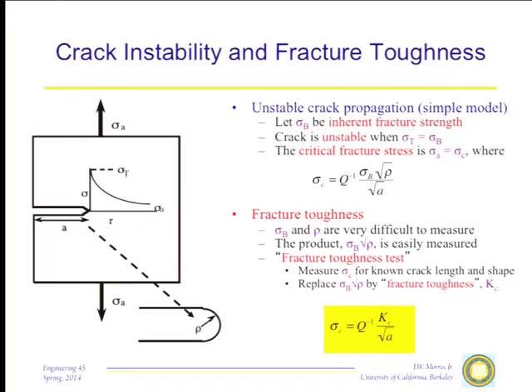Then let me just do a test. I put a crack in of known length and known geometry. I load it as sharp as I can make it, load the sample up until it becomes unstable. So I've measured sigma c, I've measured Q, and I know A. So I can therefore measure the fracture toughness Kc. Now that's the product of a couple of things I'd have trouble measuring individually, but I don't really care because what I want to know is this. I'm going to be able to predict the breaking stress. So this is what's called the fracture toughness.